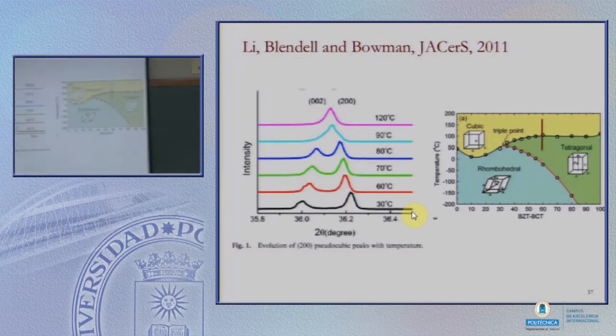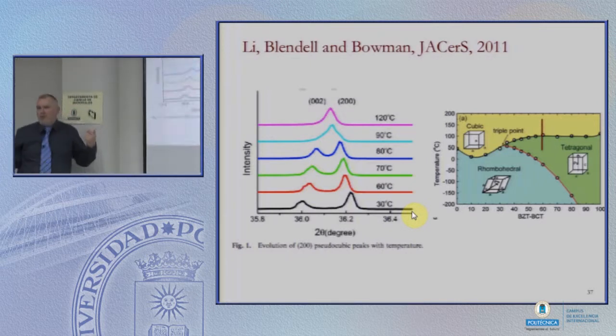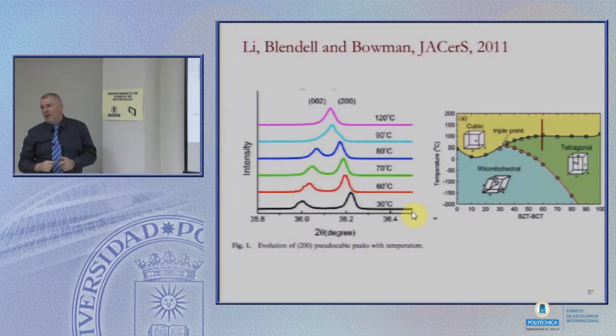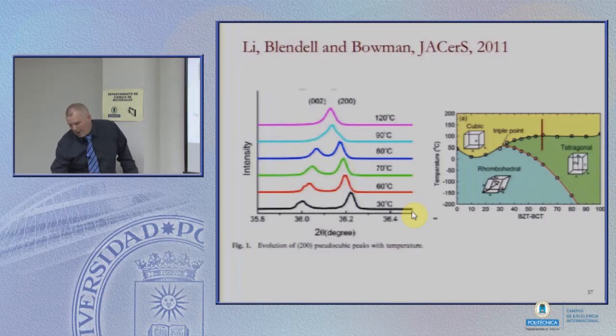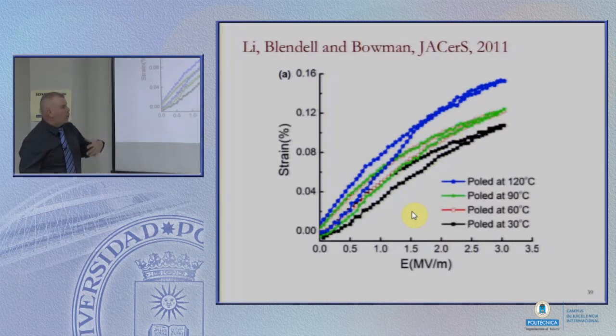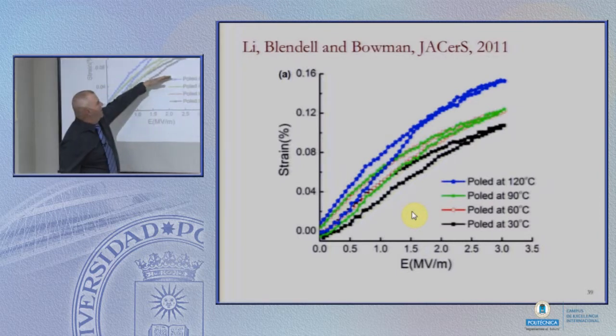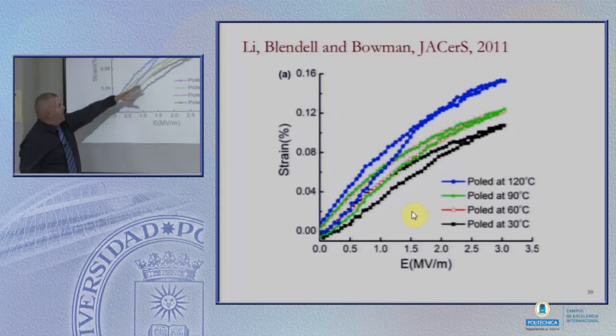So then there's the question, if it's cubic, applying a field should do nothing more than just polarize it while the field is applied. But we had questions because of the route we had used to pole the material. So if we actually go forward. So this is what we did. The method that was used by Benji is the field cooling method. So we did poling of these materials at 30 C, 60 C, 90 C, 120 C. And you're able to see that at 120 C, what we did is we applied an electric field while it was cubic and held it through temperature. So we cooled it while it was under applied field.